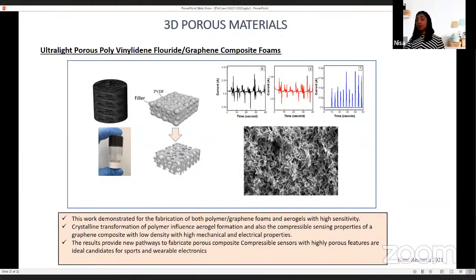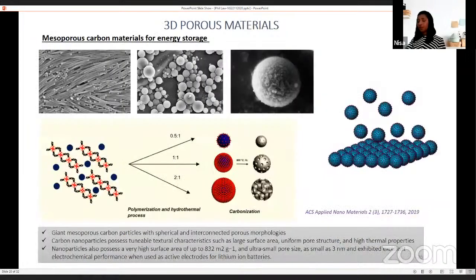So in the study, we demonstrated how the crystalline transformation of PVDF influences aerogel formation. And this material exhibited compressive sensing properties. We were also interested in looking at structural features to make porous carbon materials.